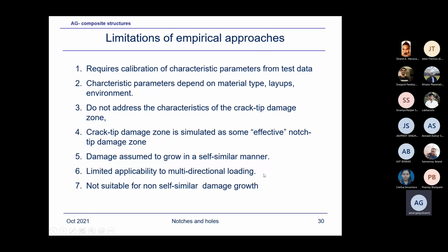Limited applicability to multi-directional loading, because our analysis methods are limited to only unidirectional loading over here and not suitable for non-self-similar damage growth. If you want to consider this phenomenon, non-self-similar, that is, the crack deviating from the path of the original crack, then these methods are not applicable. That is being predicted by using the FEM methods. There are lots of methods where crack growth studies have been done in composites.